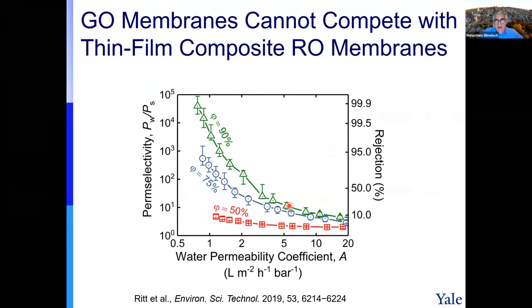I would like to summarize the data. It's a very loaded graph and I will guide you step by step. This describes the permselectivity or water-salt selectivity. Just think about it, we can translate it to salt rejection here. So think about salt rejection. And this is the water permeability coefficient. And I'm showing you the data for different areal coverage. Let's take 50% areal coverage. By the way, we use nanosheets of different sizes so we can get very high coverage, like 90%.